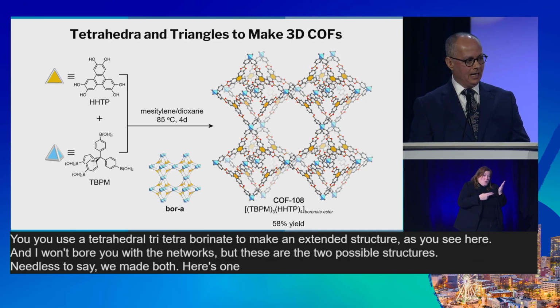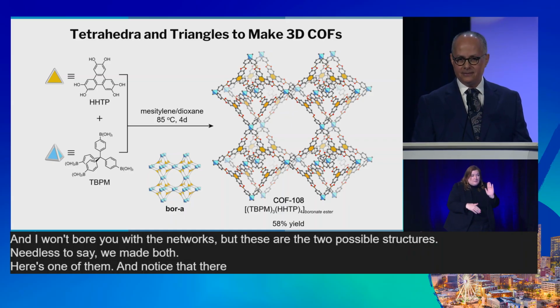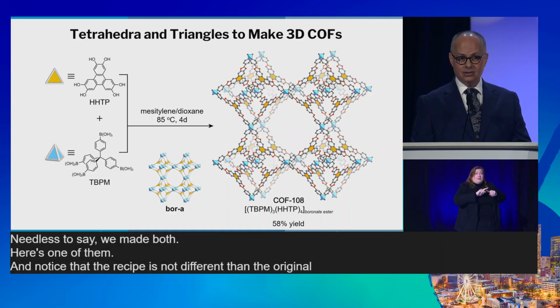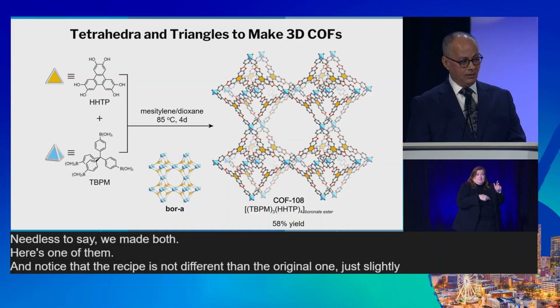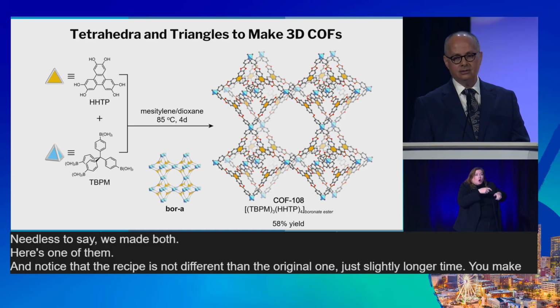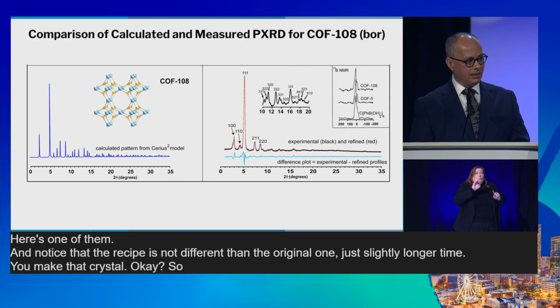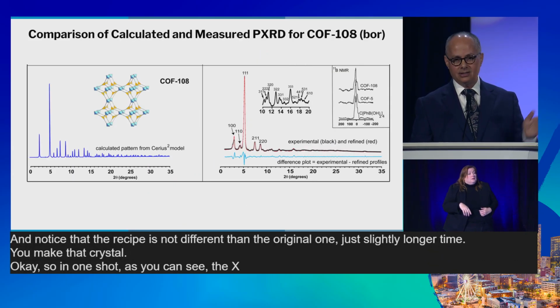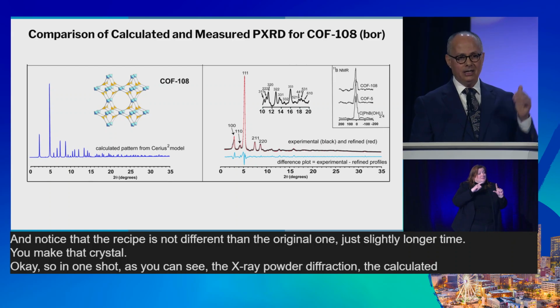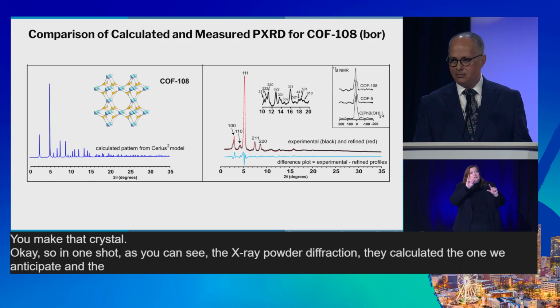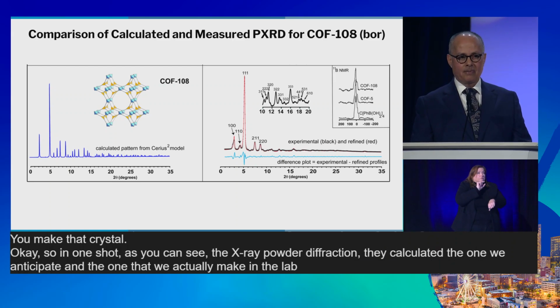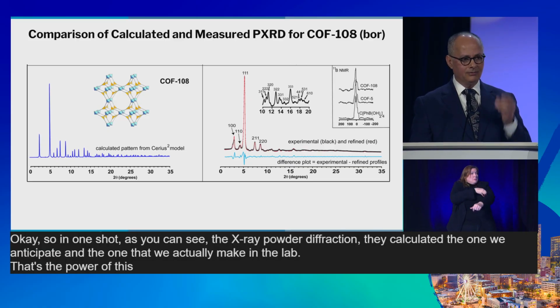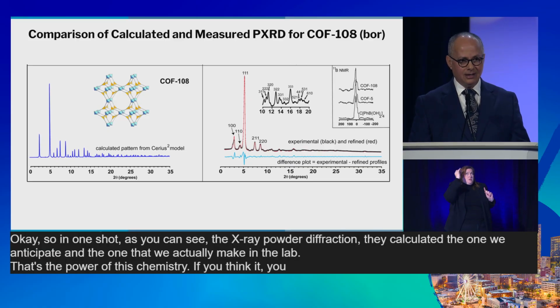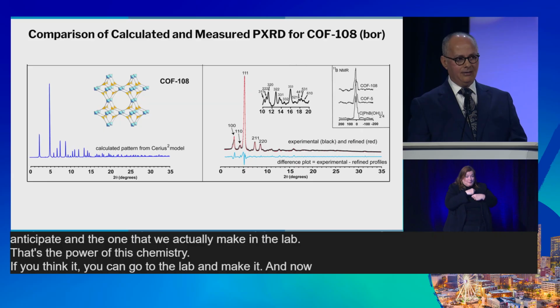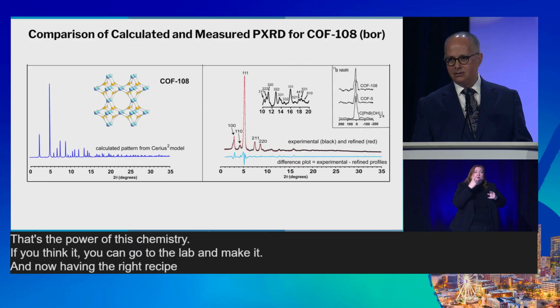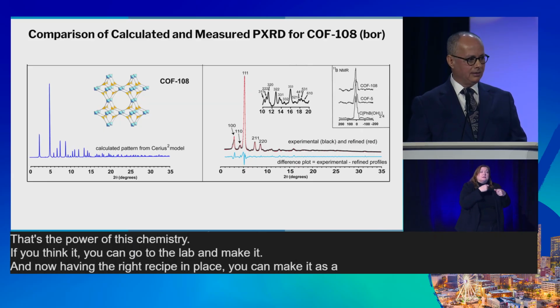Here's one of them. And notice that the recipe is not different than the original one. Just slightly longer time, you make that crystal. Okay? So in one shot, as you can see, the X-ray powder diffraction, the calculated, the one we anticipate, and the one that we actually make in the lab. That's the power of this chemistry. If you think it, you can go to the lab and make it, and now, having the right recipe in place, you can make it as a crystalline material.